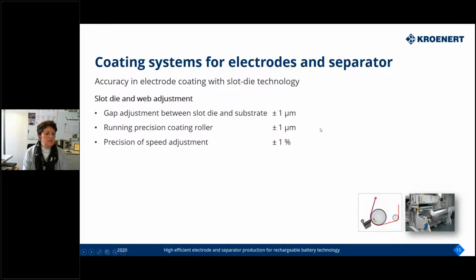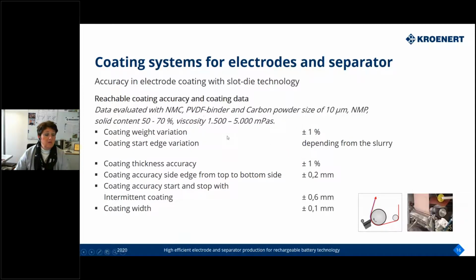Here you have some parameters showing how good we can realize such slot die technology. The gap adjustment between the die and the substrate, which means this tiny little gap, is at an accuracy of plus minus 1 micrometer. The running precision of the opposite roller is also very important because this also influences the gap between the die and the substrate. This is also running within 1 micrometer. And we also need to look at precise tension and speed adjustment, because as soon as you are not running the web at a constant speed, you will have a variation in coating thickness. This is quite difficult if it happens.